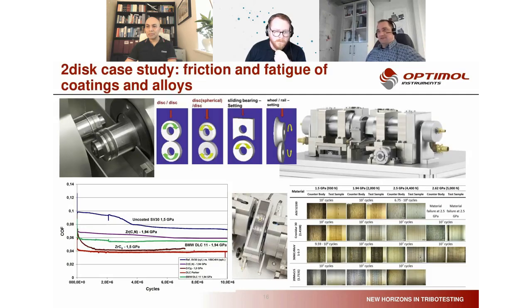As you can see here in this short case study, targeting on friction and fatigue of coatings and alloys under slip rolling conditions, where you can nicely differentiate, on the one hand side, the friction properties, and on the other hand side, fatigue damages on the surfaces, where you can see pittings, micro pittings, and of course during the running in period you see also abrasion and all other mechanisms.